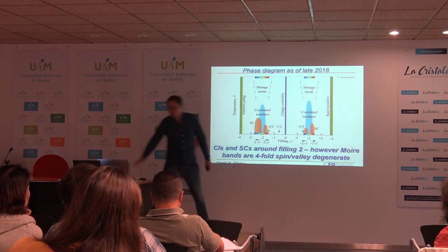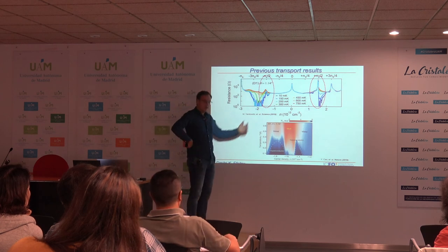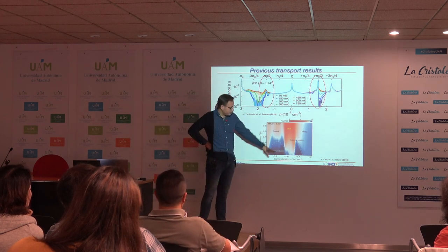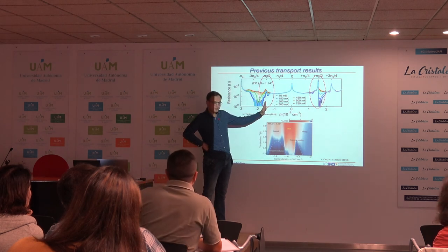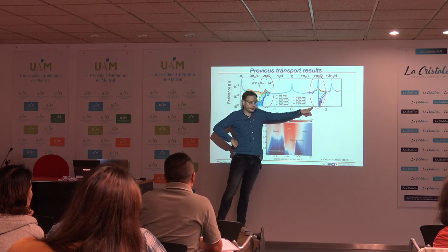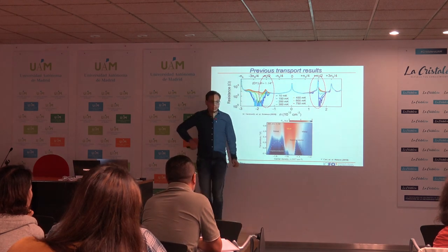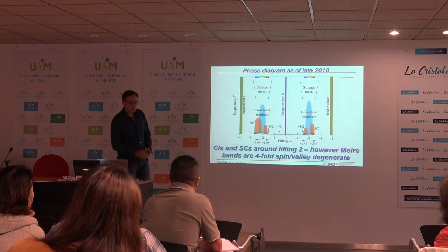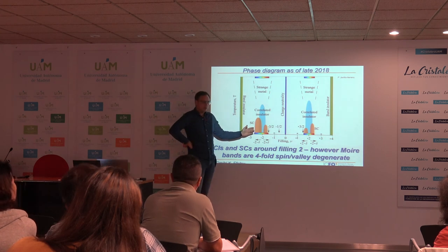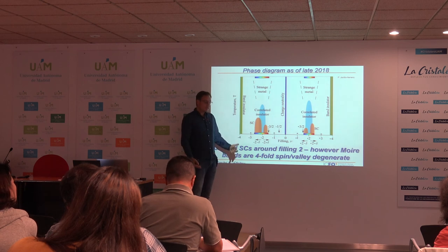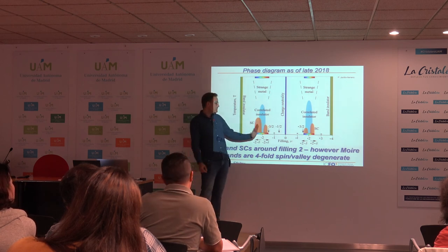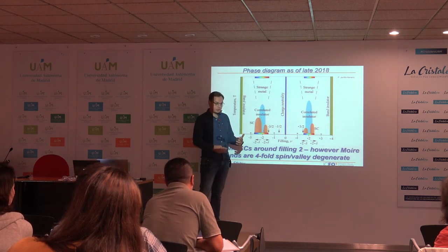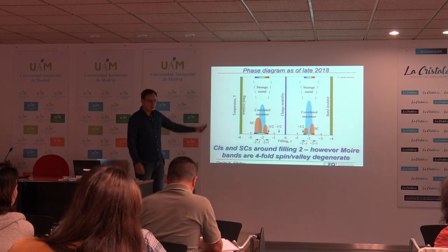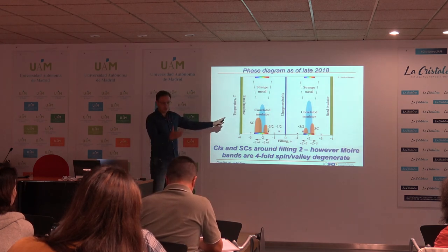And then in Pablo's original paper, in the data which he showed in his last talk, these two superconductors appear only in the hole region. In this paper, they didn't see any superconductivity signs in the electron side region. So to understand this phase diagram, you really need to understand that this is sort of a convolution of all the different samples they measured, but not every single sample shows exactly the same phase diagram. Sometimes you see superconductors only on this side, but not on the other side, and so on. So it's very sample dependent which part of the phase diagram you're actually resolving one at a time.